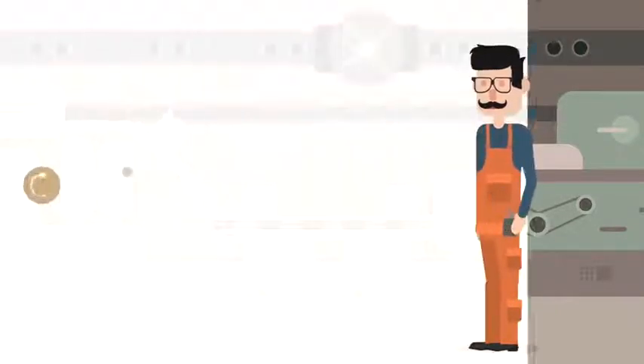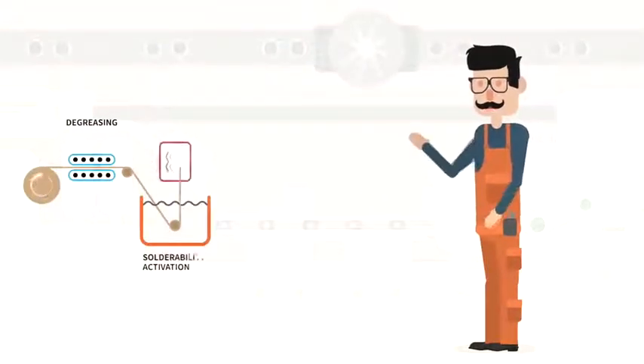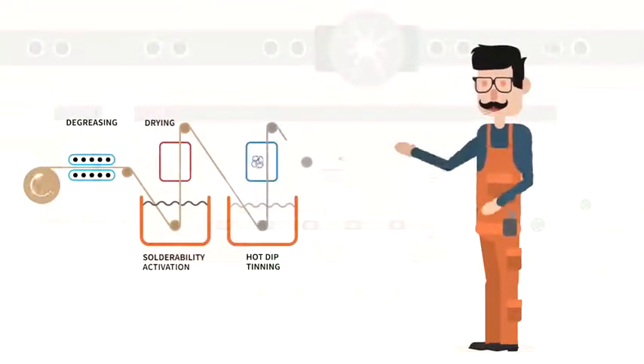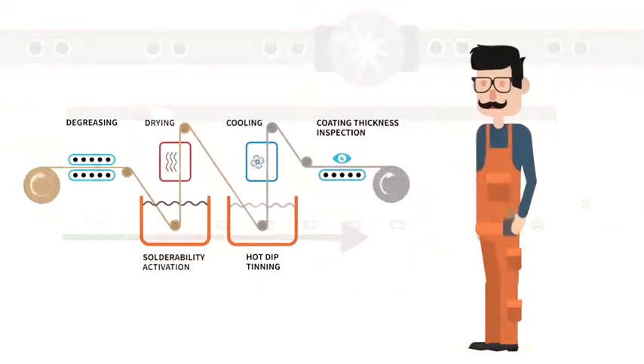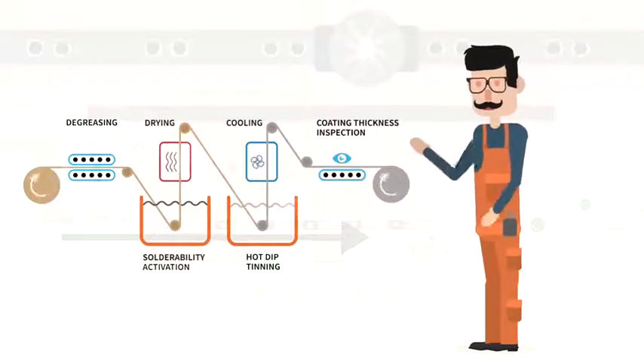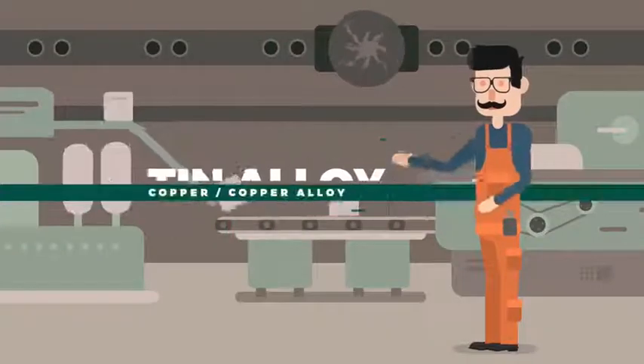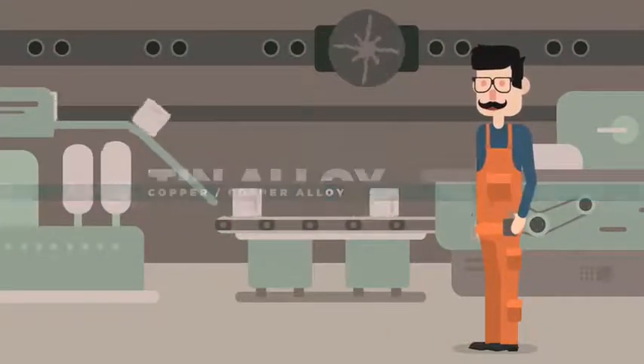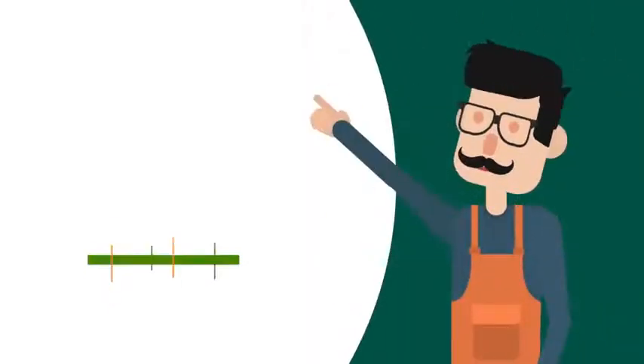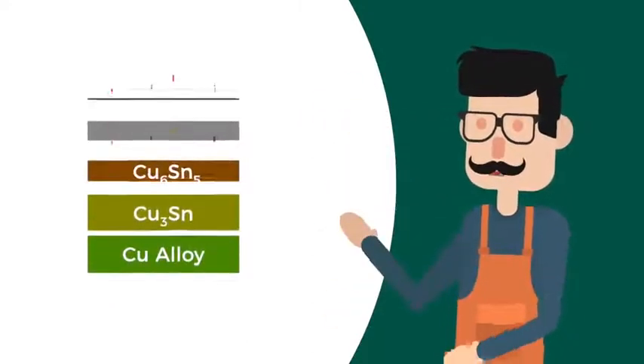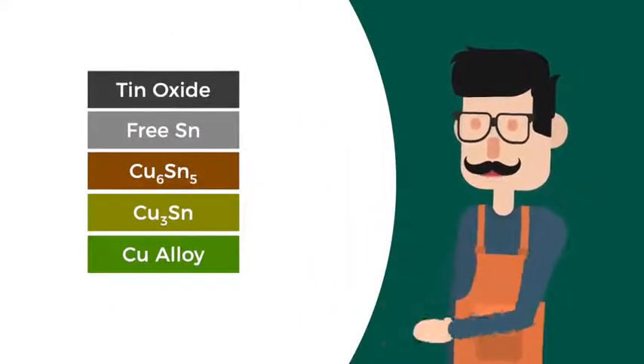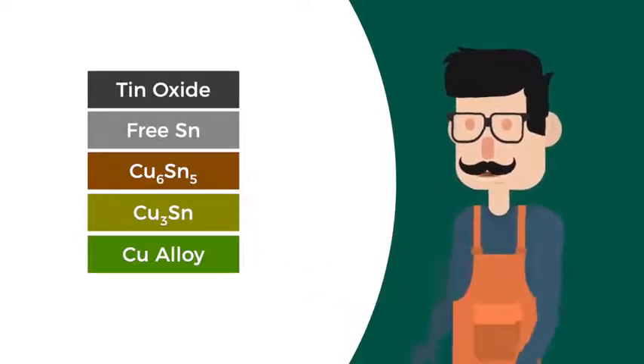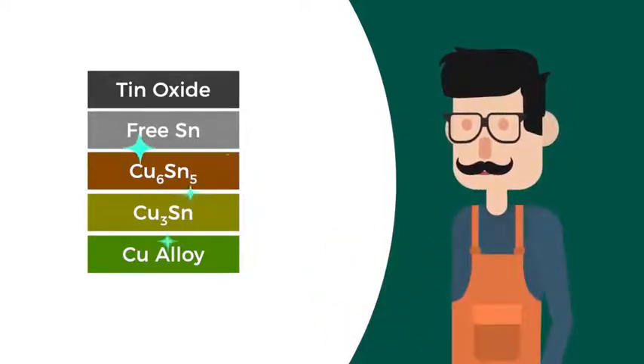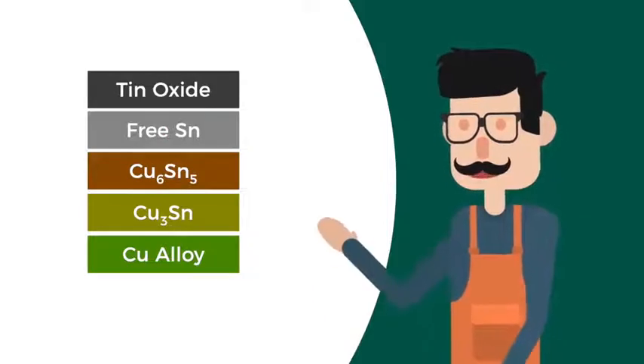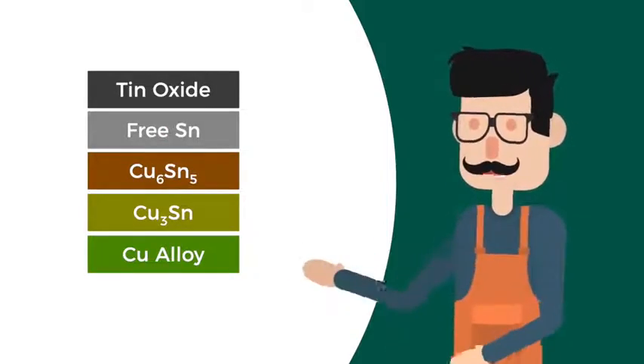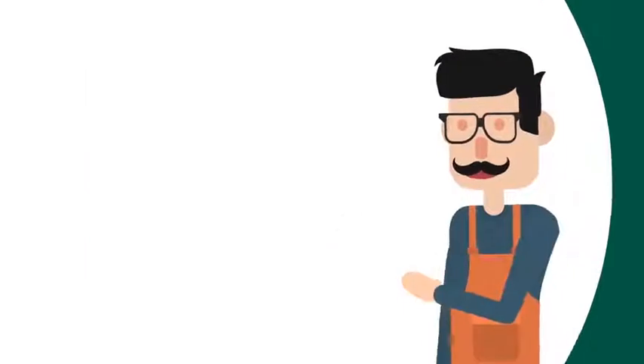KMD's hot dip tinning process is that coils go through degreasing, drying, solderability activation, hot dip tinning, cooling, coating thickness inspection, and finally become finished goods. We can plate copper or copper alloys with tin or tin alloy by this process. Comparing with electroplating, hot dip tinning can plate tin better on the surface of copper during processing. The contact layer between copper and tin will create a hard and uniform intermetallic phase, which will remarkably reduce the insertion force and resistance of the metal.